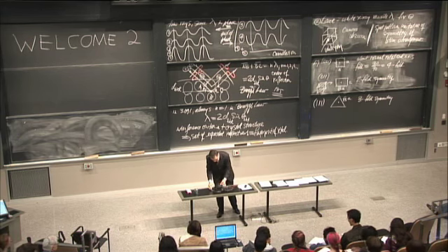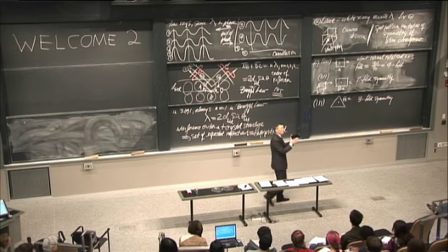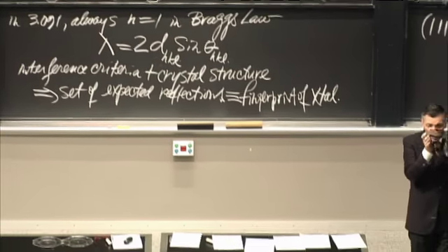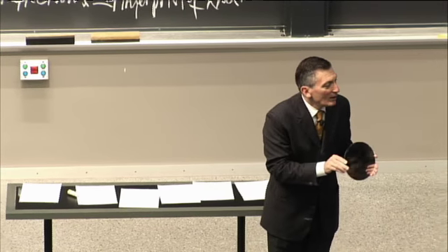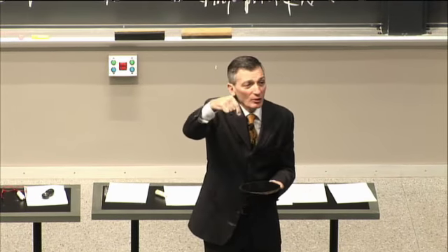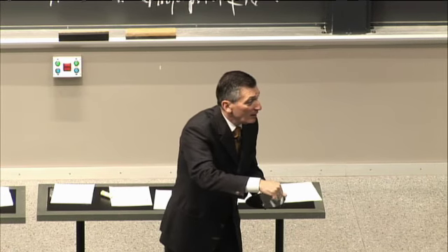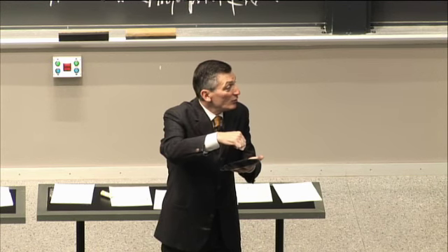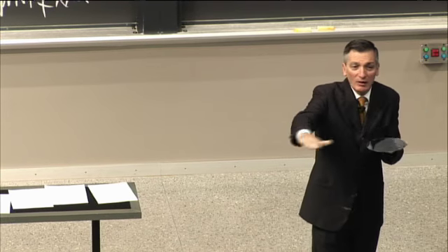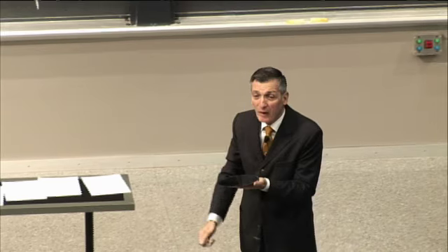And that means if I take a crystal such as this, for example, I've told you before, this is my silicon wafer. And this silicon wafer has been cut from a single crystal. So I am looking at the edge of an atomic plane. The question is, which one is it? The crystal didn't come with a label on the side. I don't know what the crystal growth axis was. I started with a single crystal, and I dipped it into molten silicon, and just like rock candy, I drop the heating coils and cause the liquid to solidify around the seed crystal, and I grow this salami that's about 8 inches in diameter, about 2 meters long. Now I go and I cut these things with a diamond wheel. So I'm cutting them normal to the growth axis, but I still don't know what plane I'm looking at.